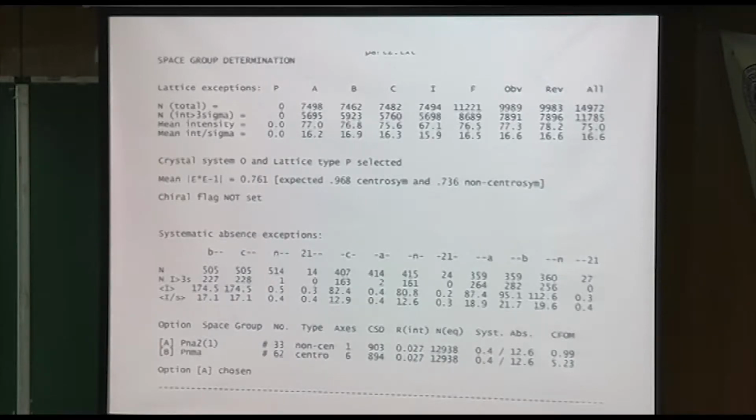But the N, remember, itself is a diagonal. But it's because it's in the A slot that tells you how it reflects. There's also a 2-1 screw axis in the same slot there. So which one do you put in? Do you put in the N or the 2-1? Well, it turns out that the N is what is recommended, although 2-1 also exists in the same direction. So that's confusing enough. But if you have access to the international tables, you could see that both of those are listed. Then there is also an A glide, which is a translation along A, but it's in the B